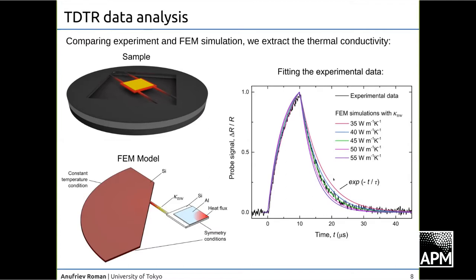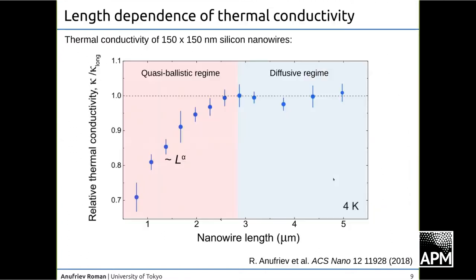So thermal conductivity is like a free parameter in the simulation. Of course, it's an automated process. It's not like I'm looking at the curve and deciding which one fits. It's fully automated, but the principle is this. So the experimental result. First, let us start from the very low temperature where we expect the longest mean free path of phonons, where we have the longest phonon wavelengths and everything is supposed to be more ballistic than ever.